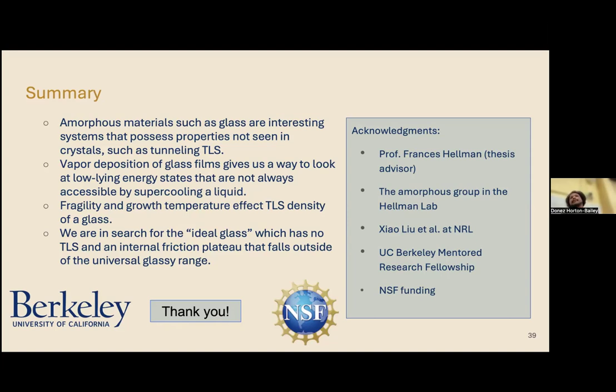They were candidate materials for LIGO. So currently LIGO uses silica and tantala, I believe, silicon dioxide and tantalum oxide. It's a complicated number. And I should have mentioned that the mirrors they use are what's called a Bragg reflector. So you have an alternating set of layers of high index of refraction and low index of refraction materials, and you stack them up, and you're able to get a very high reflectivity mirror. There were talks about possibly changing the material inside to improve the mirrors, and aluminum oxide specifically was a candidate material, based on some old sputtering data, but it turns out after the work that I've done that it's not actually feasible.